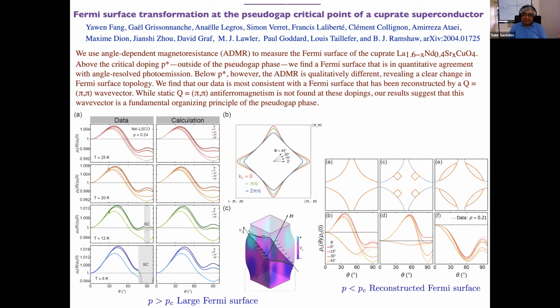However, if you look at low doping, then you find these full lines here, I believe, are the theoretical fits. The dashed line is the data. If you take at that density the corresponding shape of the Fermi surface with density 1 plus P, it simply doesn't work at all. This is some other model corresponding to small hole pockets that doesn't work very well either. What does work is this one. The Fermi surfaces are small, so I'll refer to this as a small Fermi surface, and that fits the data beautifully.